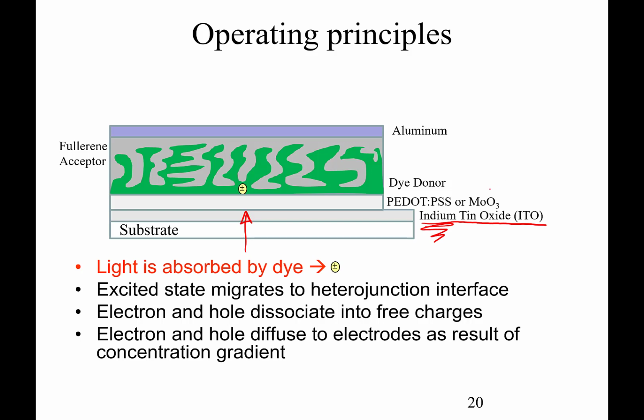We use molybdenum trioxide very often in industrial manufacture. We use something called PEDOT-PSS. It's essentially a buffer layer, and it allows holes to move through in one direction, prevents electrons to move in that direction, and so that means that the electrons end up having to go towards the top, towards the aluminum. Getting ahead of myself, so the idea here is we have light comes in through the bottom, and we have the dyes that are in this active layer. Here's our active layer, and those materials in that active layer end up absorbing that light.